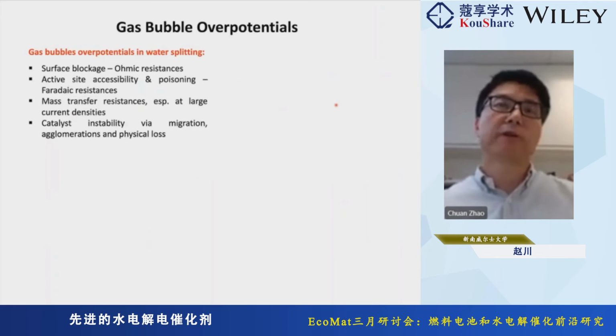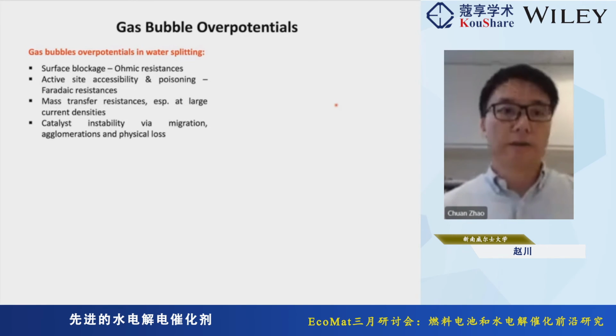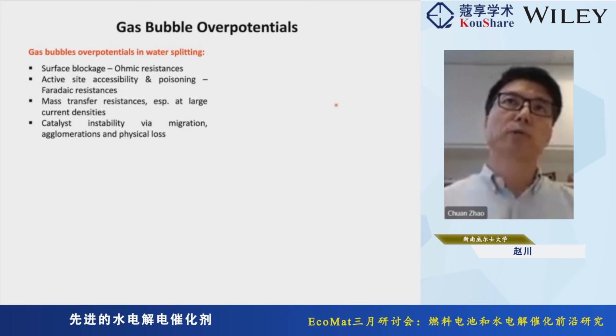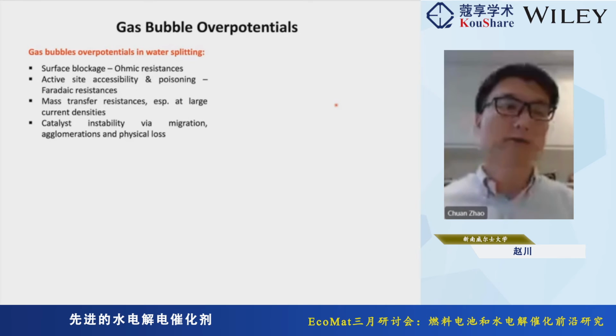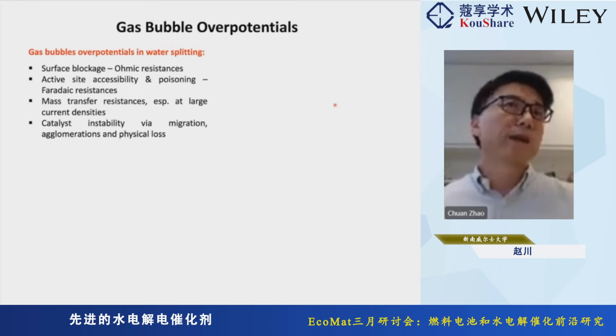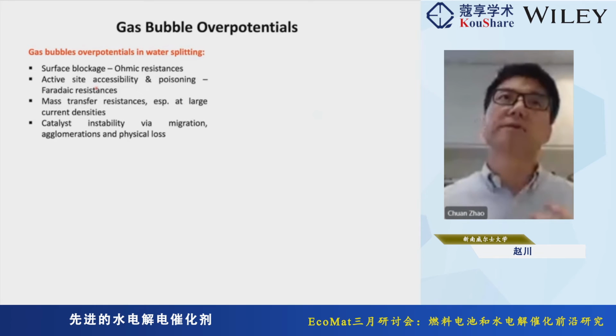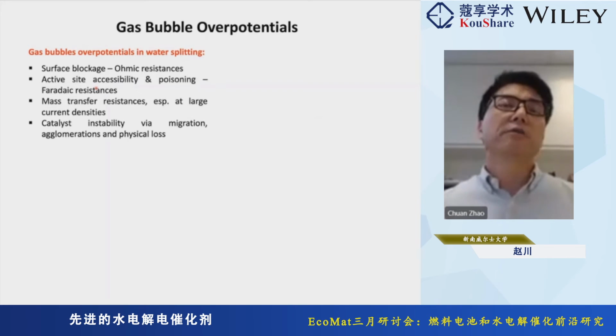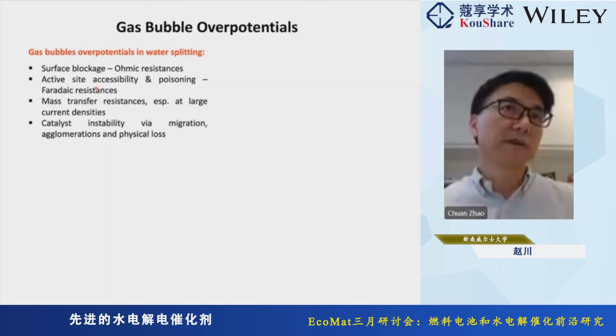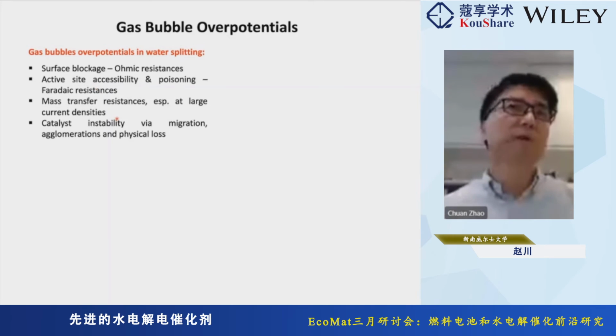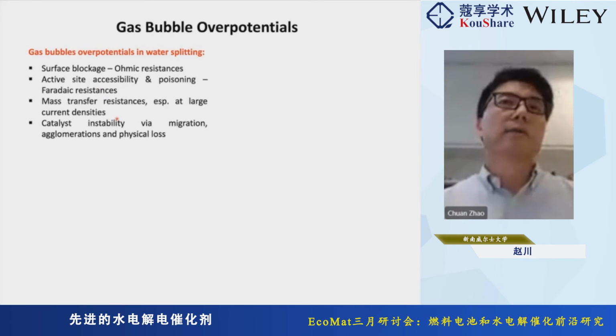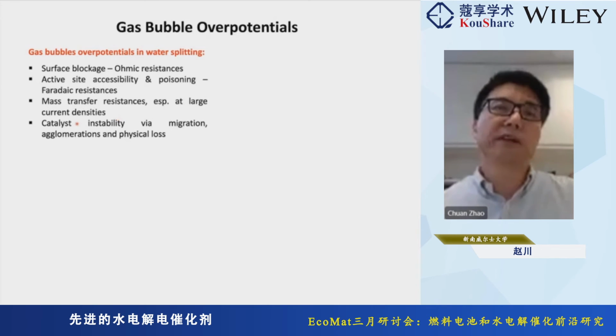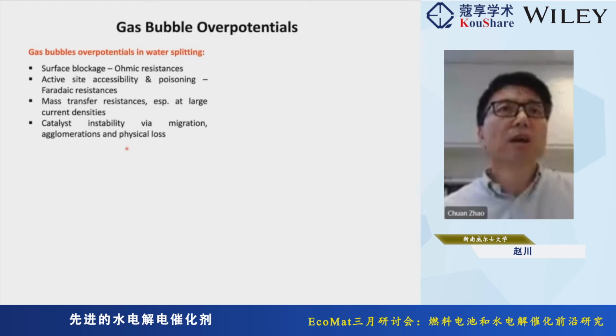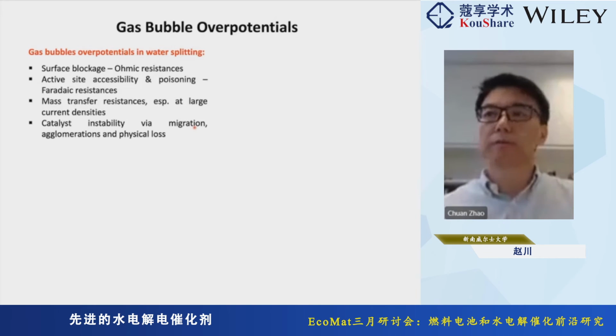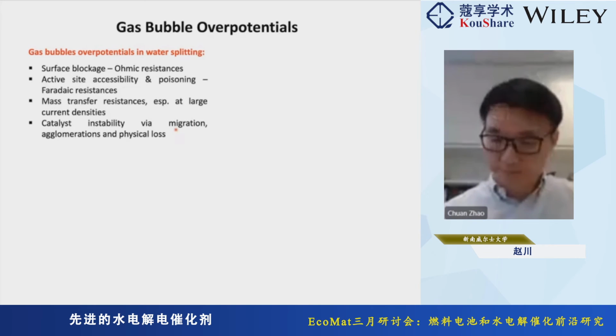So another advantage we found with nickel molybdenum iron is that it also reduced the gas bubble overpotential. Gas bubbles are actually quite a big problem in water electrolysis. The gas bubble is hydrophobic. It can adsorb on the solid surface, block your active sites, and introduce ohmic resistance, but also Faradaic resistance. It blocks the mass transport of your electrolyte, and also can cause significant deactivation of the catalyst by migration, aggregation, or simply physical loss of the catalyst.